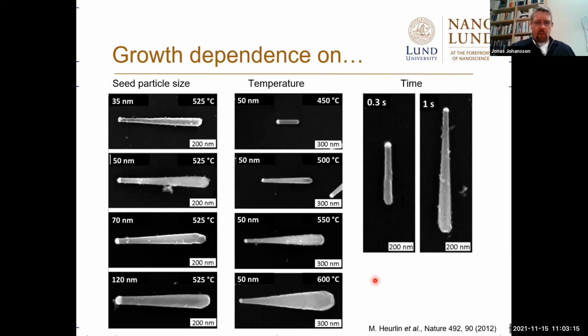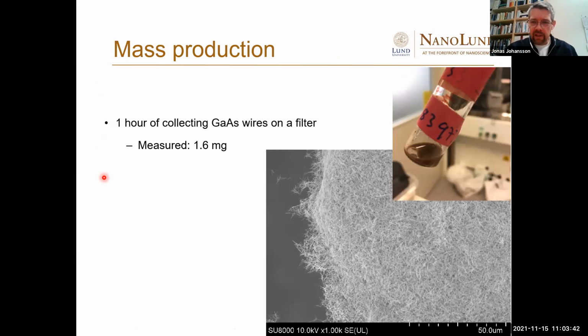And we see that the growth depends strongly on temperature and on growth time, of course. But if we look at growth dependence on seed particle size, there is no significant dependence. And we can get a lot of nanowires. So this is the result of 1 hour of collecting gallium arsenide wires on a filter. So we get about 1.6 milligrams.